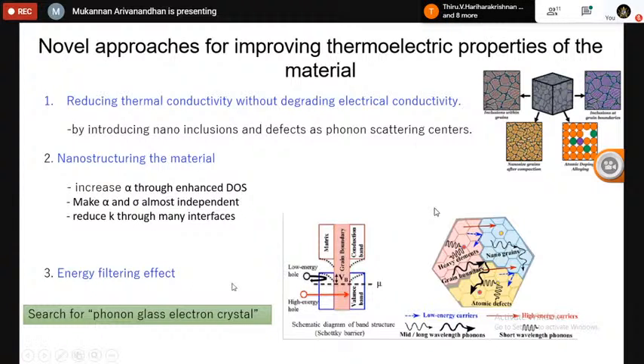And the energy filtering effect, that is another beneficial aspect of nanostructuring the material by creating a lot of interfaces. So these kind of grain boundaries will act as some kind of potential barrier for the carrier. So based on the energy of the carrier, the high energy carrier may go through the potential barrier, whereas the low energy carrier may not. So like that, some kind of selective transport can be realized, and that will lead to improve the thermoelectric performance of the material.